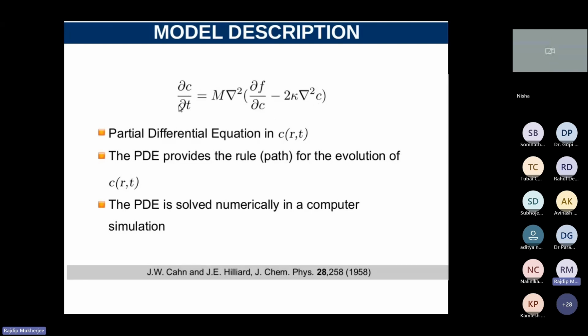So if we solve this simple equation with proper initial and boundary conditions, we can actually observe the spinodal decomposition. But we need to know the free energy of the system. We need to know some data, the interfacial energy. We also need to know the atomic mobility or diffusivity parameter. So if you know the thermodynamic and kinetic parameters, we can actually observe this microstructure evolution during spinodal decomposition. So here we solve the partial differential equation, and the PDE provides the rule or path for the evolution of composition, and the PDE is solved numerically in a computer simulation, right?